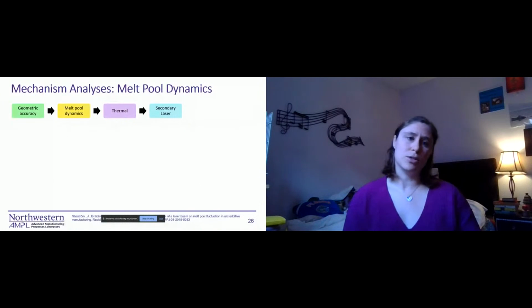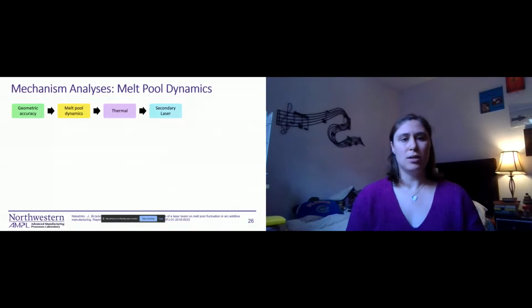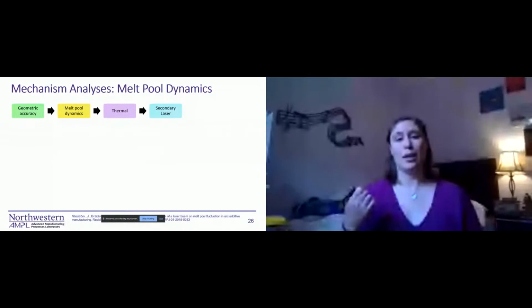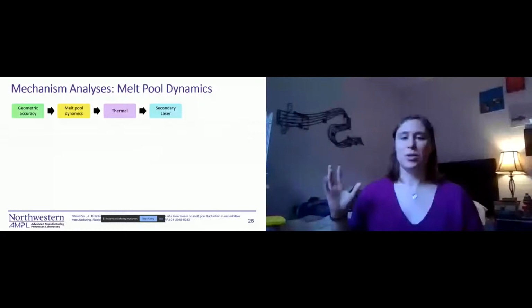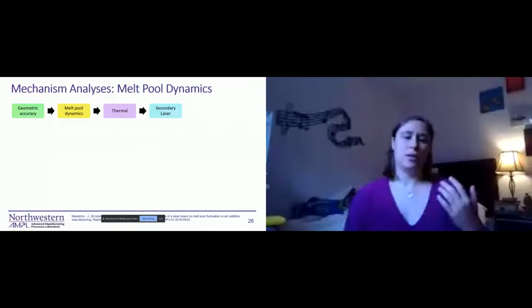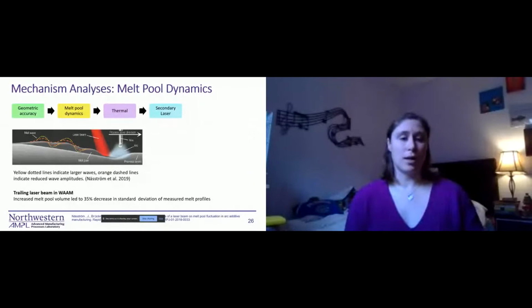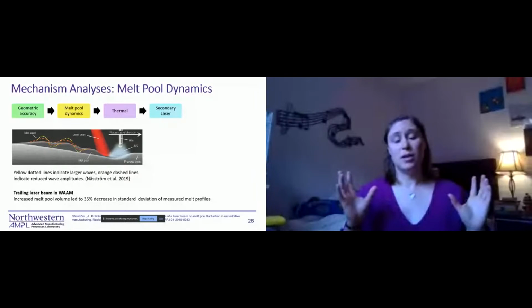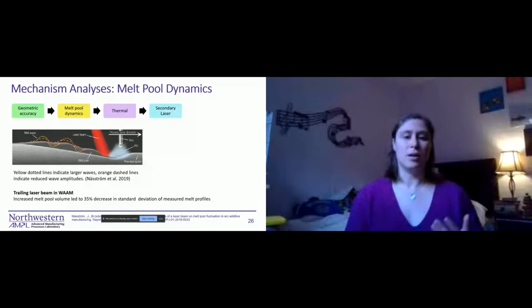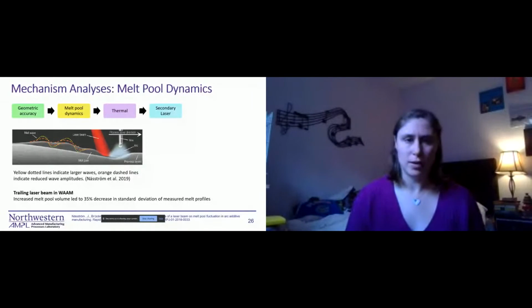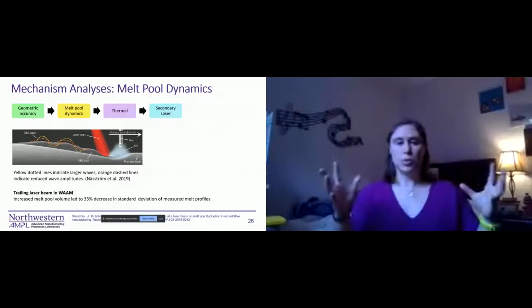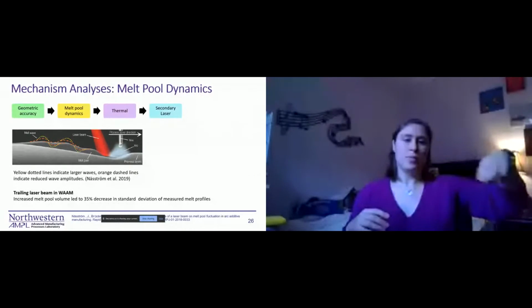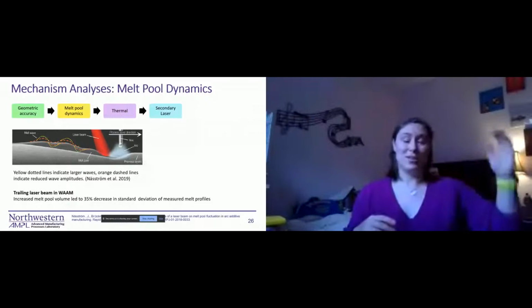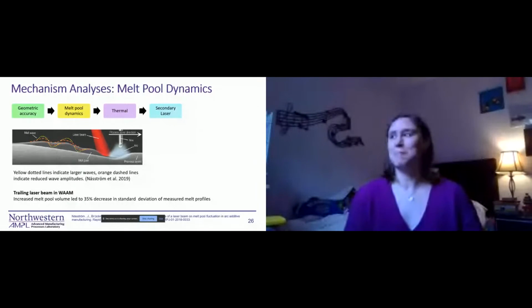The second example is looking at geometric accuracy that was influenced through melt pool dynamics using a thermal energy source in the form of a secondary laser. So this process was wire arc additive manufacturing with a trailing laser beam. And essentially, this not only increased the melt pool volume, it also led to a 35% decrease in standard deviation of the melt profiles. So since the melt pool was larger, it was not as wavy behind the process.